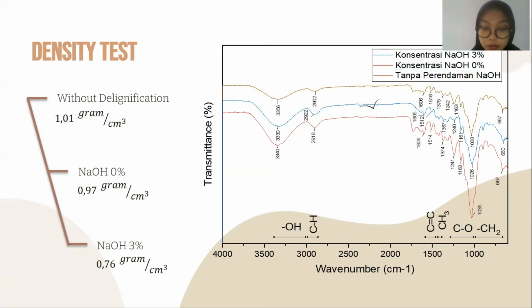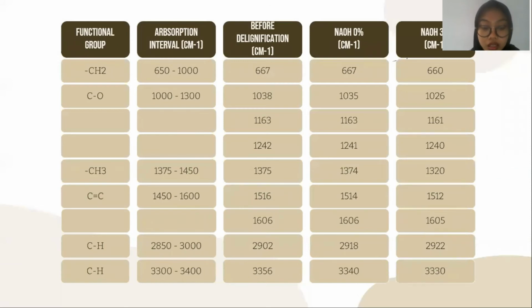And then the graph on this slide is the spectrum from the FTIR test. The red line on the graph is the FTIR result of the fiber after delignification with 0% natrium hydroxide, and the blue line shows the FTIR result with 3% natrium hydroxide delignification. And this is a table showing the peaks of the FTIR result graph.